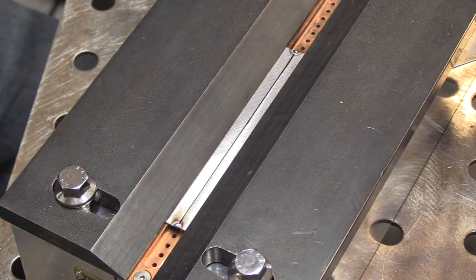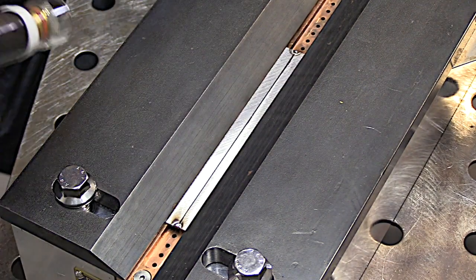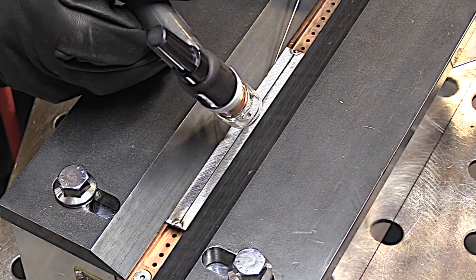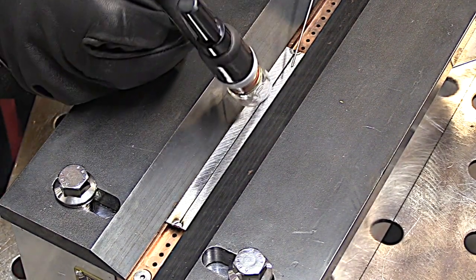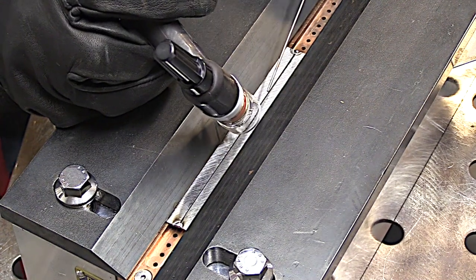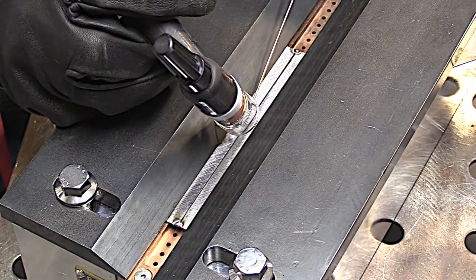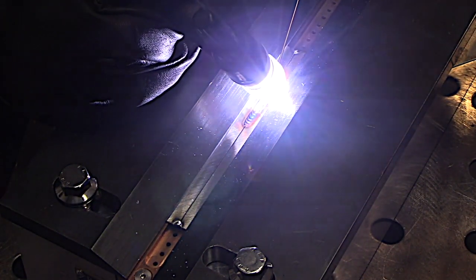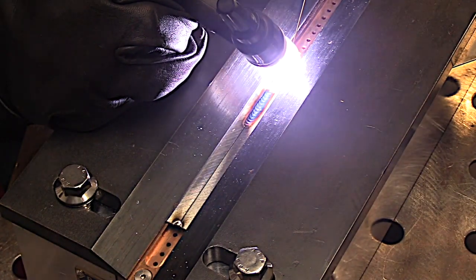The aerospace welding specification allows for some melting ends away, but when I used to administer this test, I didn't allow that because all of our parts had ends that we didn't want to melt away. I was probably lenient in other areas that I didn't feel were as important, but melting ends away is something I felt was super important. So the way we administered this test was to start in the middle and weld to one end. That way we could require a stop and a taper off and a crater out taper off in the middle to demonstrate the ability to not leave a crater crack, which is another thing I felt was super important on aircraft parts.